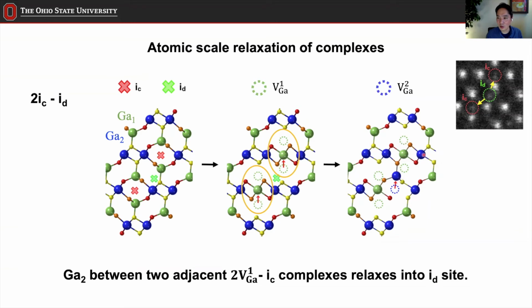So now, that's this one right here. So what you're looking at here is the ID site intensity from right here, which is this one, and two IC site intensities, which are this and this. Okay, so they're always paired. So this is kind of a secondary relaxation that we saw here, and it is experimentally seen. So we wanted to calculate the energy of the whole formation, but that was actually very difficult to do. Perhaps I should ask Hartwin to try it, but our collaborators so far were not able to deal with the large structure in their DFT simulation. So it was pretty difficult.